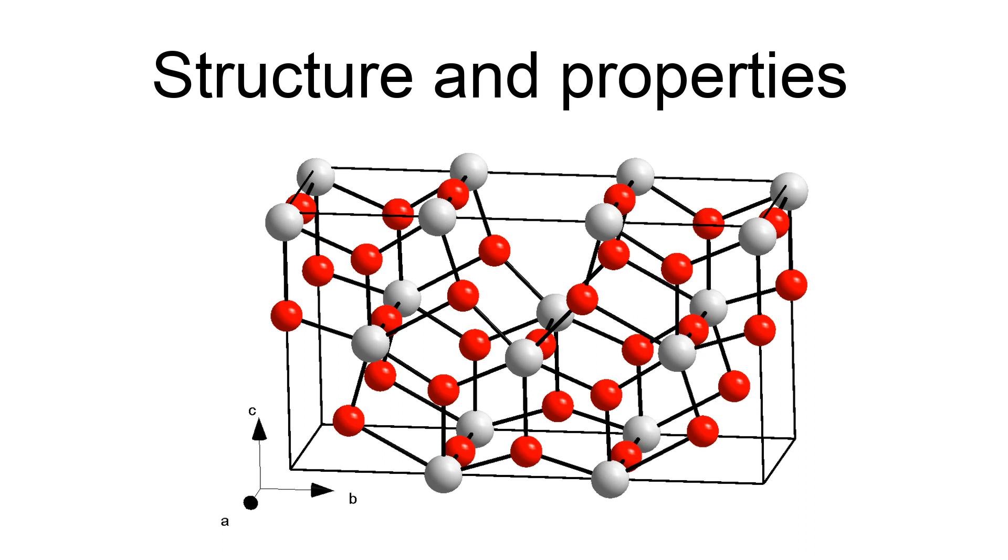The structures of both polymorphs consist of chains built from octahedral Ta-6 and pentagonal bipyramidal Ta-7 polyhedra sharing opposite vertices, which are further joined by edge sharing. The overall crystal system is orthorhombic in both cases, with the space group of beta-Ta₂O₅ being identified as Pna2₁ by single-crystal X-ray diffraction.